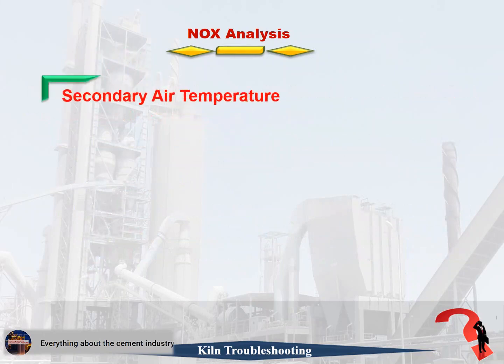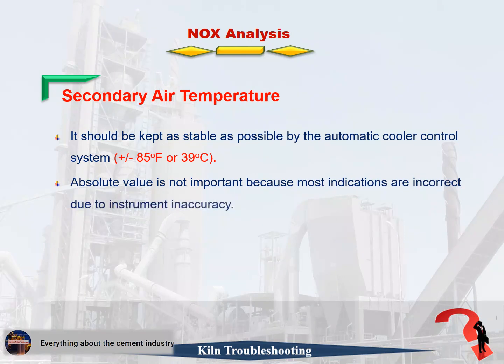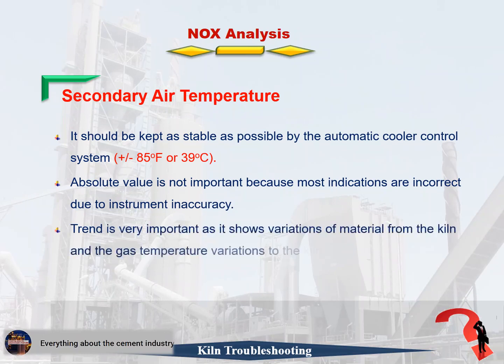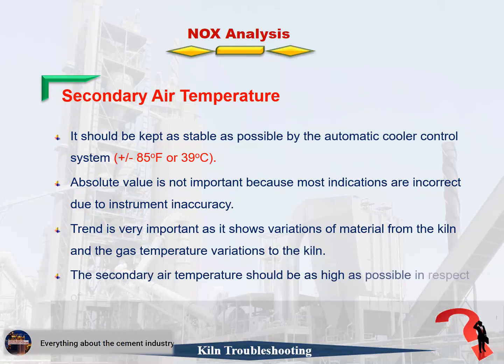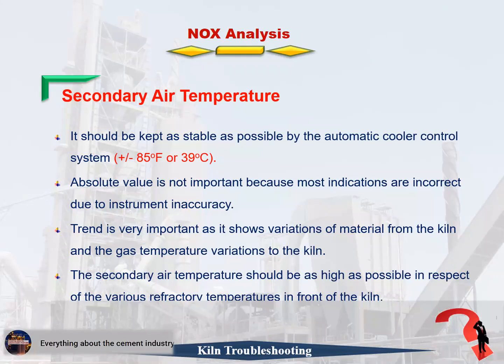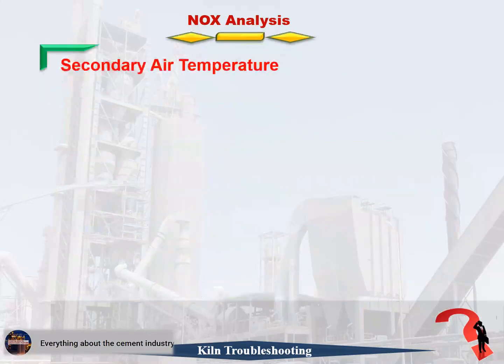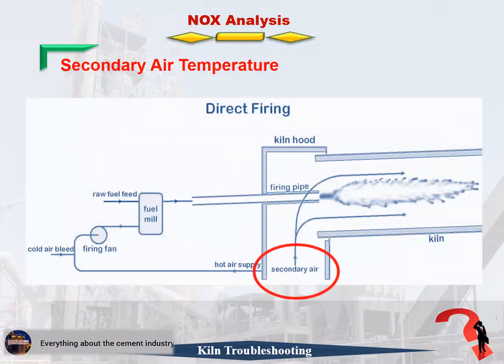Secondary air temperature. It should be kept as stable as possible by the automatic cooler control system, plus or minus 39 degrees. Absolute value is not important, because most indications are incorrect due to instrument inaccuracy. Trend is very important as it shows variations of material from the kiln and the gas temperature variations to the kiln. The secondary air temperature should be as high as possible in respect of the various refractory temperatures in front of the kiln. This picture shows secondary air temperature.